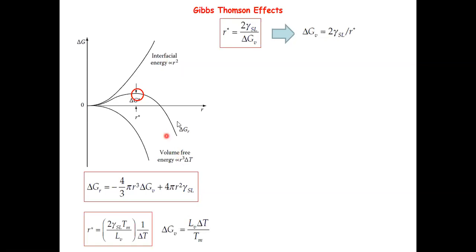So we know that the system is definitely going to have a lower free energy for a large nucleus, and for a very small nucleus, you have the opposite situation, right? R squared is going to dominate because it's going to be larger. So the smaller nucleus is not favored, and based on this analysis, we know that this overall free energy as a function of the nucleus size has to be a non-monotonic function where you have a local maximum, right here,